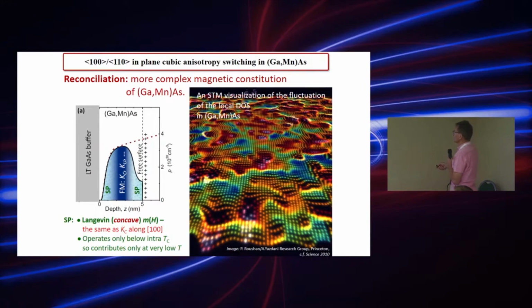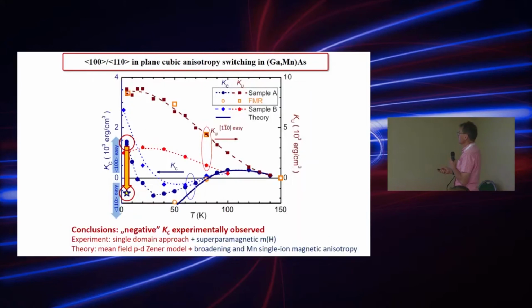But what you see is that many of these hills are separated from each other. So if there is a ferromagnetic coupling, it's at best only percolation-like, and there is no way of assigning a global coupling. This superparamagnetic contribution gives another concave component to our magnetization, and in our understanding, it is this superparamagnetic concave character at low temperatures that pushes the cubic constant to appear positive. So when we compensate for this effect, our points really go down to negative values as the theory predicts.